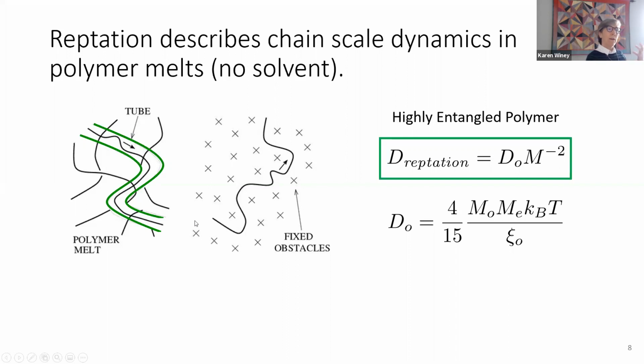We can approximate these entanglements with these cross marks, and the polymer chain has to wiggle its way through. Anyway, this is a well-established model. The reptation model goes as this D naught, which has the frictional coefficient and the temperature dependence in it, to the molecular weight to the -2 power. This is how polymers move in a high molecular weight, well-entangled polymer melt, so in the absence of any solvent.